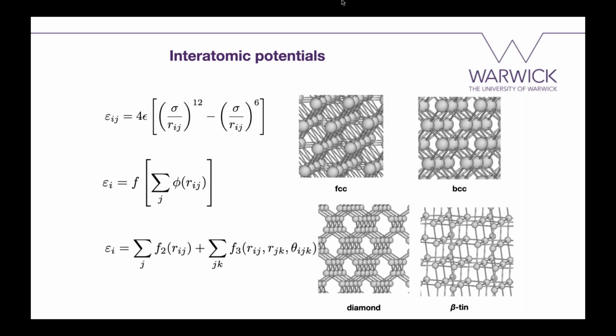We can, for example, use the embedded atom model, which is the second one, which will describe BCC metals very well. In other situations, we need yet other functional forms. For example, if you take a diamond configuration, you would need to introduce also directionality. That requires yet another functional form. But again, this also breaks down when you want to study a phase transition from a diamond type configuration to beta tin. There, the fixed functional form won't work anymore. So basically, we have this limitation that no matter how good physics we put into the functional form, as the circumstances change, our model should change as well.